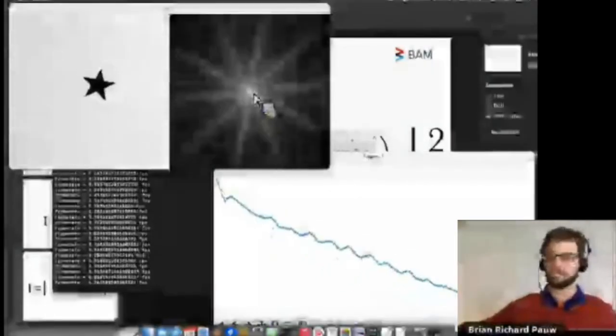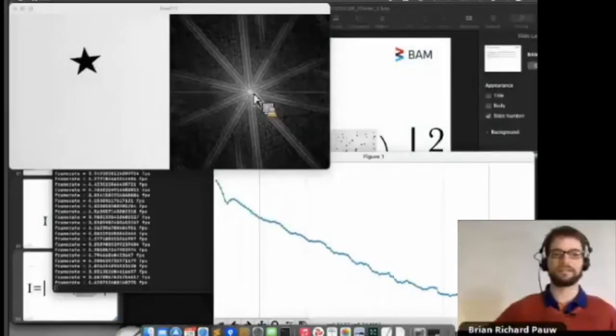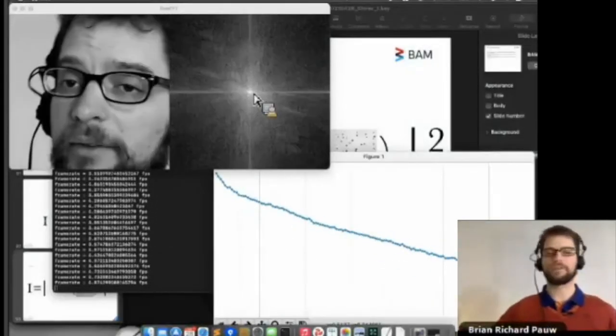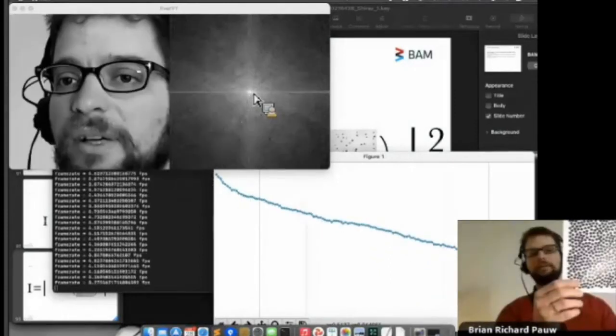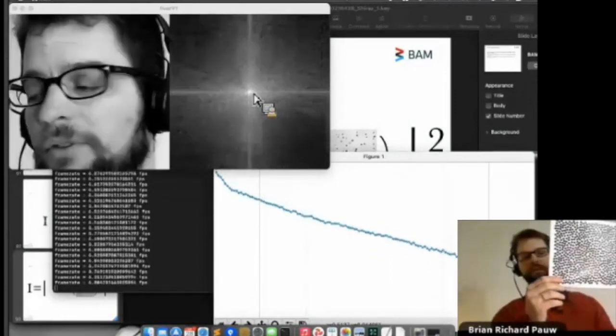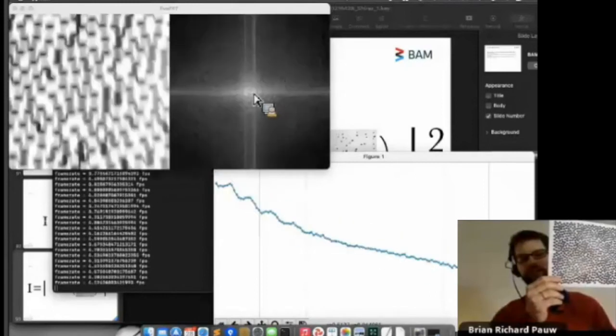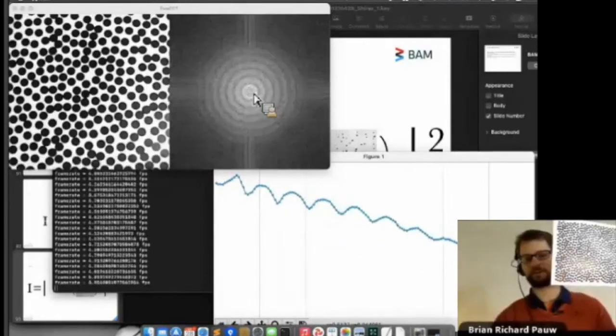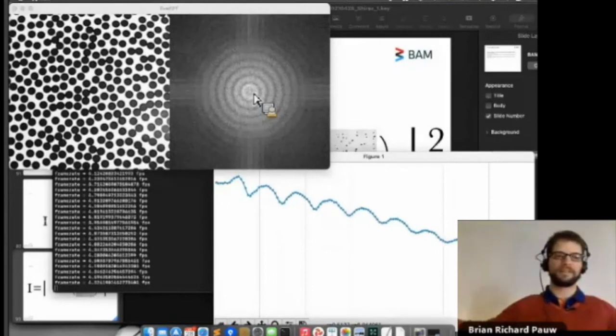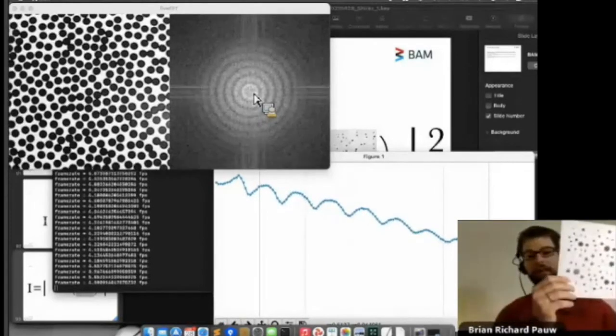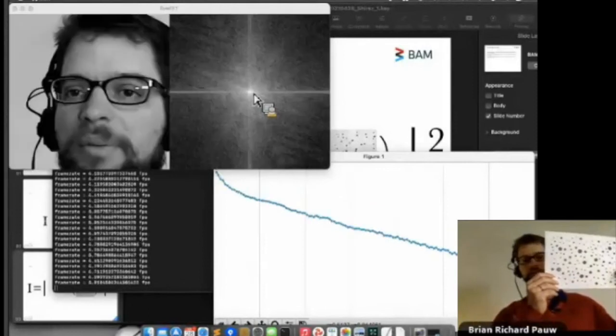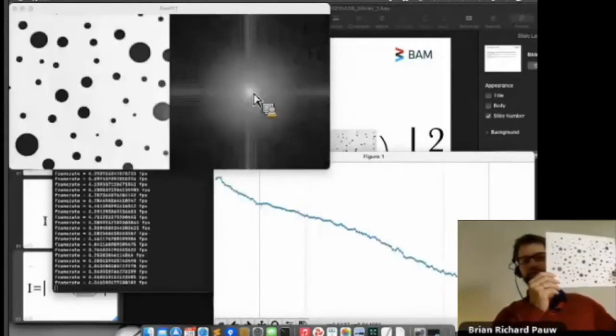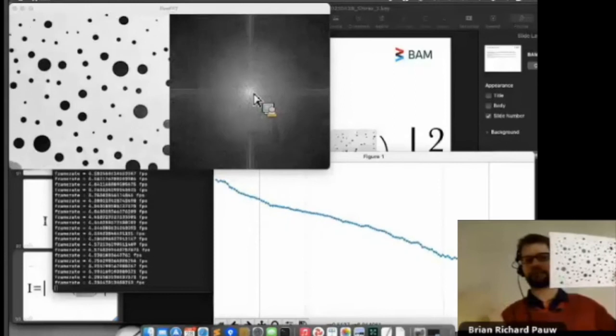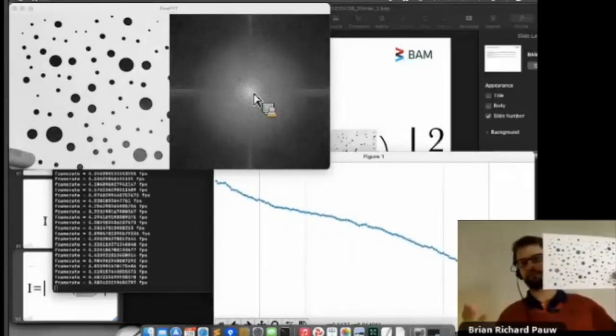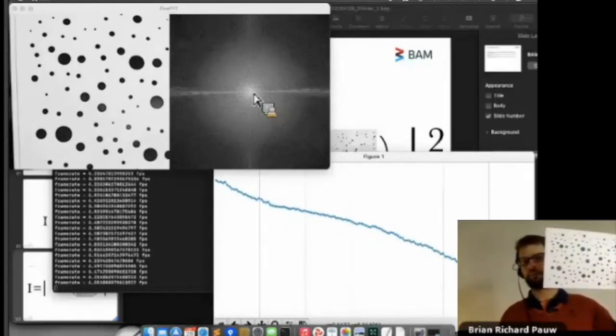However, we usually don't have one object in our scattering pattern, in our structure. We usually have more. So if we have a concentrated system of particles, we still see these nice oscillations that can tell us something about a particle shape. But if we have polydispersity in there, we don't see this anymore because all of these oscillations from each individual object start overlapping. So our information now is sort of convoluted with the size distribution.